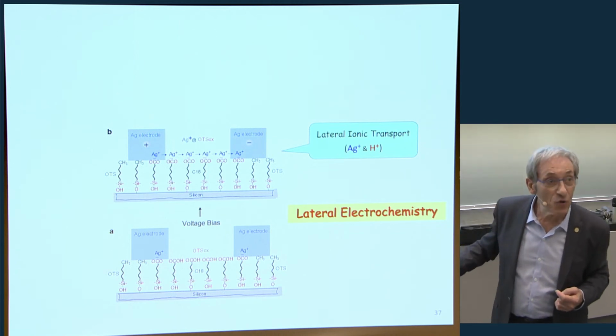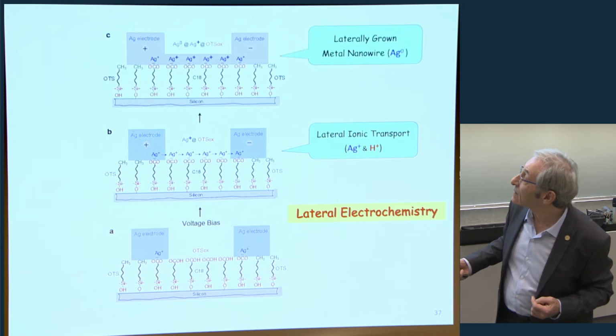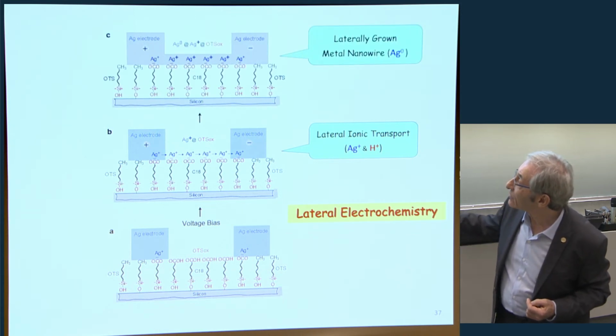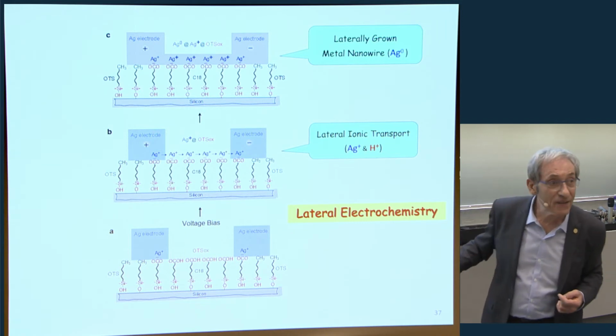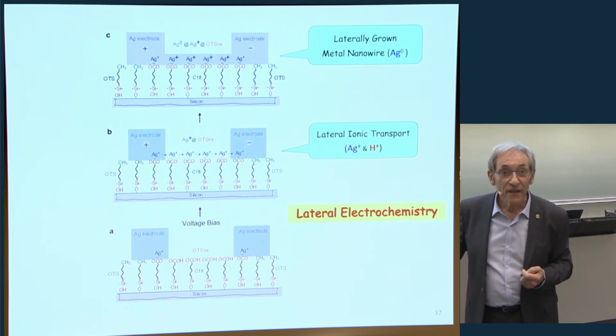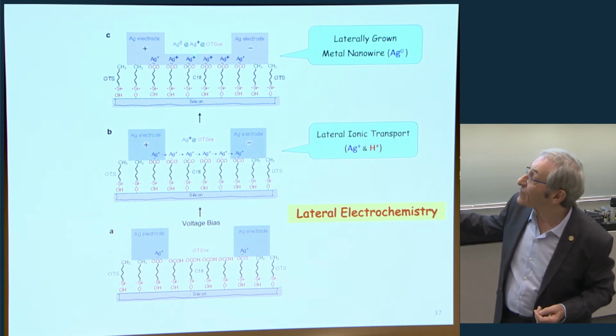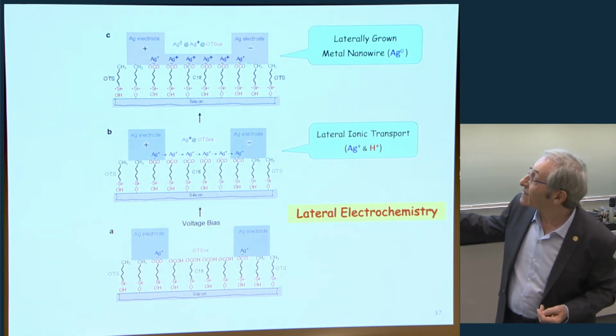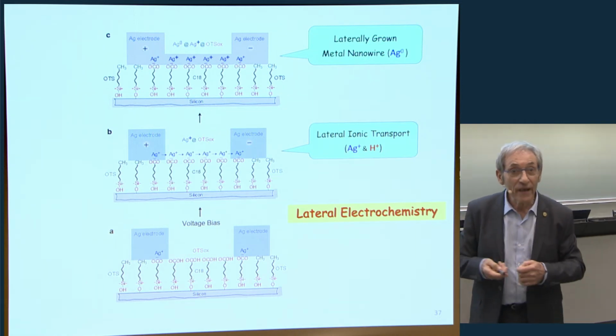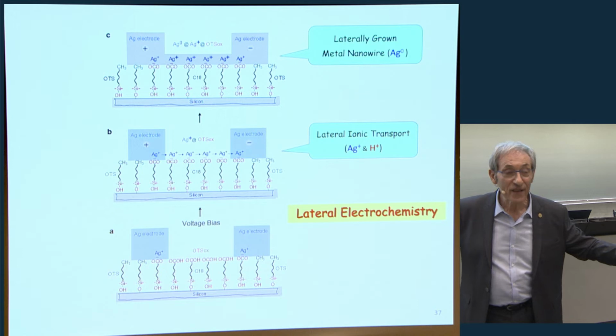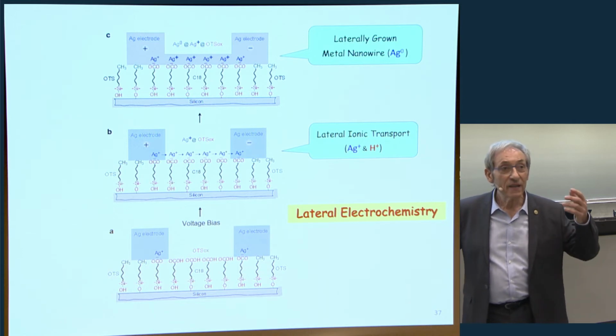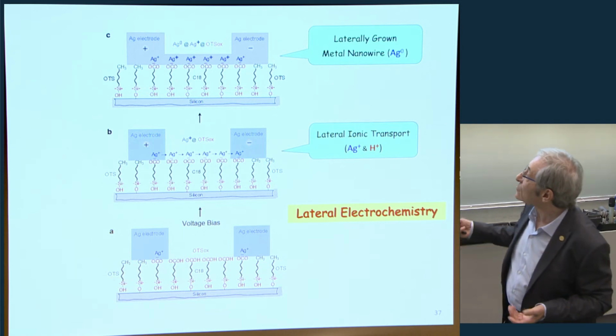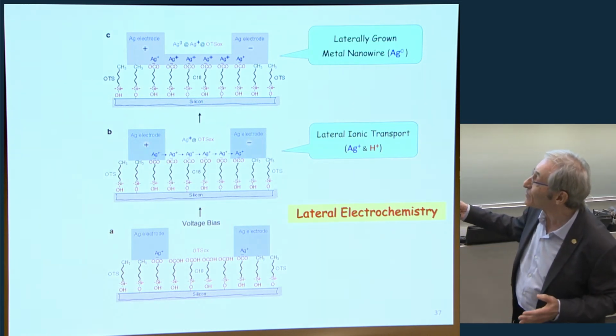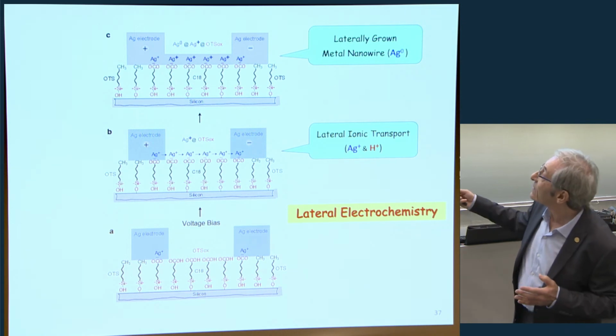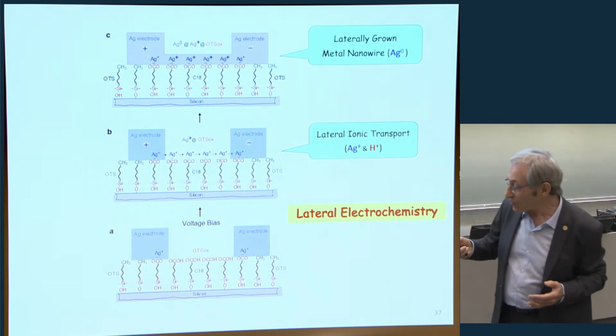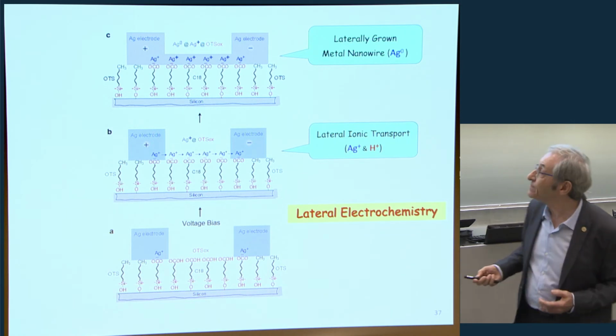So ions indeed move, but then when a silver ion arrives at the negative electrode, it gets an electron, is reduced. And then instantaneously, a silver filament builds from the cathode toward the anode, and we create now a nanowire of silver automatically, and this is a very fast process, and then the electronic transport takes over. Without the lateral ionic transport, this would not happen. But then we have a laterally grown metal nanowire, and now the action starts.